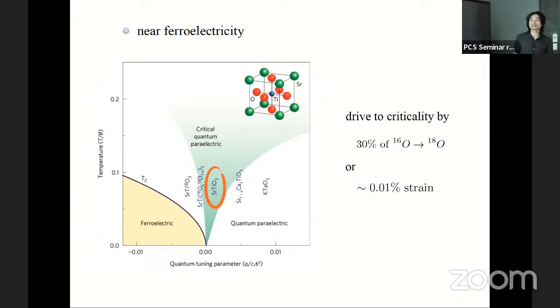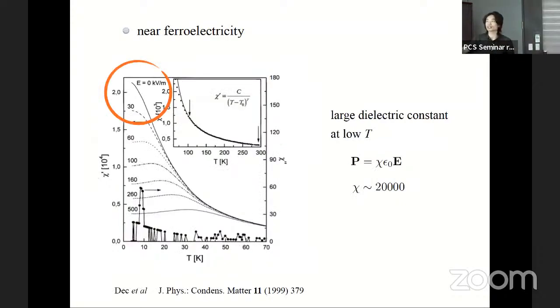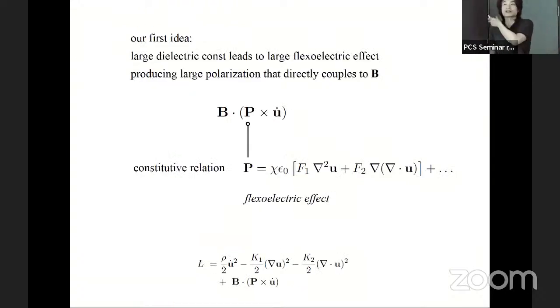Because of this, it has a large parameter, which is the dielectric constant. It is very large, because that means the positive and negative charges in the unit cell are very easy to move. And it turns out that at low temperatures, the dielectric constant is 20,000. So indeed, there is a very large parameter here. Okay, so how might a large parameter help with the thermal Hall effect?